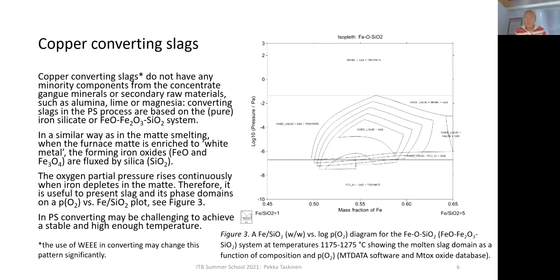antimony, bismuth, and such trace elements, but no MgO, no alumina from the gangue, no extra silica from the gangue. They all are dissolved already in the smelting furnace, in the smelter slag, and removed from the raw material feed of the converting step. So that is why it is very straightforward and a simple solution to use the same flux for iron oxides as we use in the smelting step.